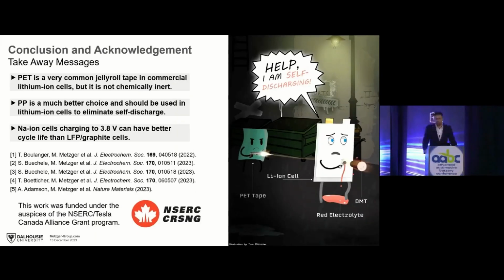Okay, so in summary, I wanted to show you that PET is a very common polymer in battery cells, and it really needs to be eliminated from those cells because it leads to self-discharge. Polypropylene is a much better choice. We recommend that cell manufacturers use that tape. It's almost the same cost, only has advantages. And sodium-ion cells that are charging to 3.8 volts can have a better cycle life than LFP graphite cells.